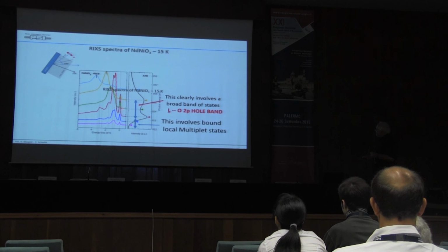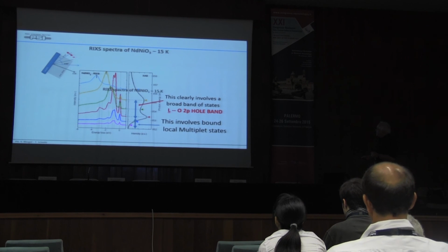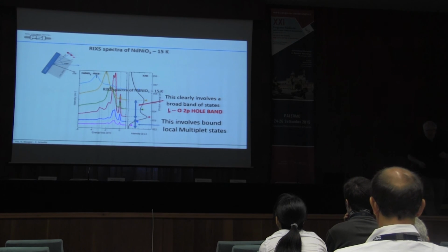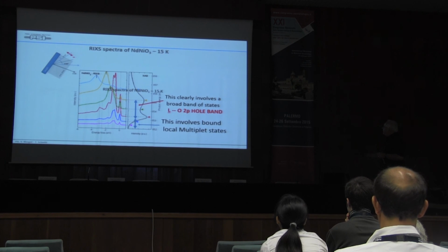So what this resonant inelastic X-ray scattering experiment does is it looks at the excitations of this system, as a function of where you are in energy in this intermediate state. If it was only multiplets that you were seeing, then you should see all these very sharp little peaks over here, and they should be independent of the incoming energy. Now what you see is that as long as you are in this part of the spectrum, they are independent. Yeah, the red one, the blue one, the purple one. But as soon as you go into here, zoop, it just disperses out with energy. Meaning, those are completely different states.